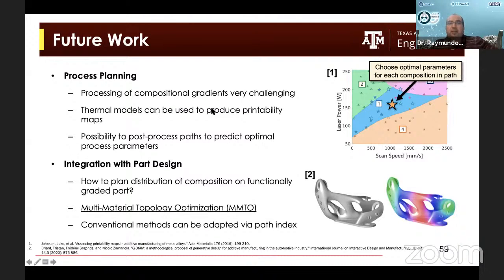We can potentially use thermal models to produce printability maps. This is work that we have done for powder bed fusion, but we are actually working right now to build printability maps for DED. Okay, and the idea was to actually come up with post-process paths to predict optimal process parameters once we have a composition path.